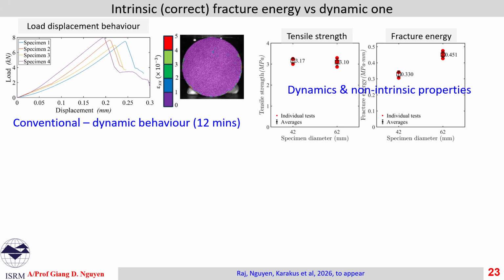So we perform a few things here to validate the determination of both the indirect tensile strength and fracture energy. The results presented here are from a conventional Brazilian test. It is very fast, 12 minutes, and we got the indirect tensile strength and fracture energy in this case. But because of the sudden fracture and violent dynamic behavior, the obtained fracture energy in this case is not intrinsic. It includes the dynamic effects.